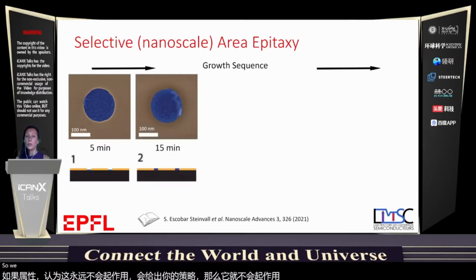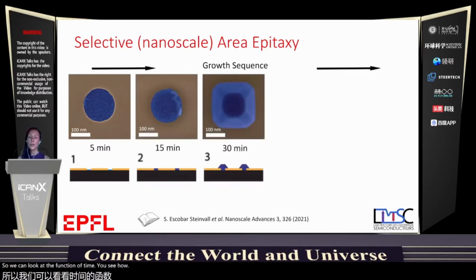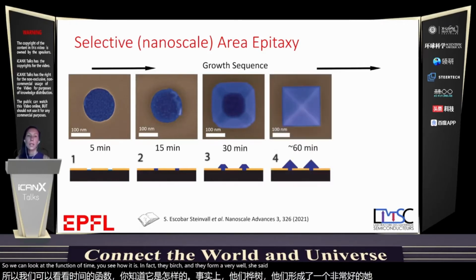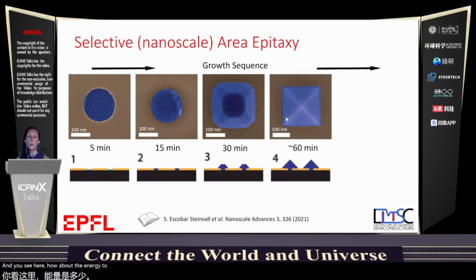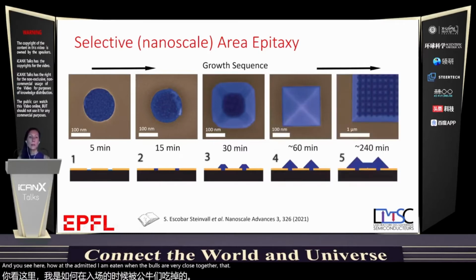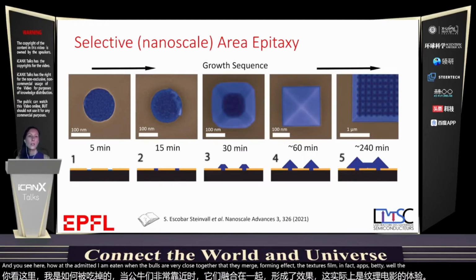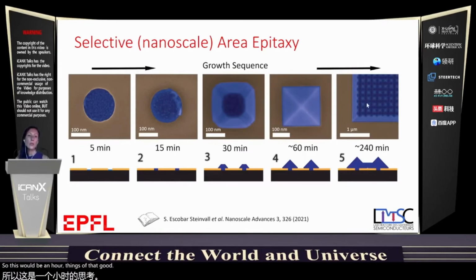If you look as a function of time, you see how they, in fact, merge and form a very well-faceted crystal. You see here how at the end it creates a pyramid, and when the holes are very close together, they merge, forming a textured film that traps light very well. So this would be a thin film that we would use for the solar cell device.